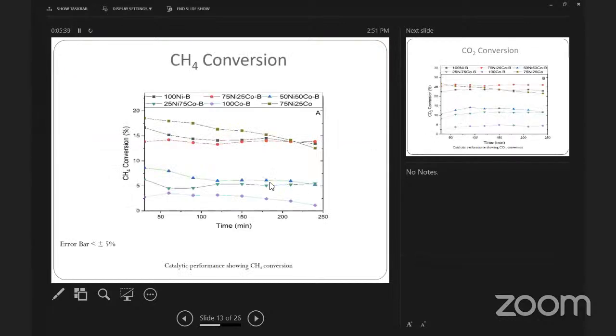Here's the result I got from my reaction studies. We have performed all catalysts, and also compared them with the non-boron catalyst, the catalyst for which we have not used NaBH4. Here we can see that with the NaBH4 treated catalyst, there is a smaller decline compared to the catalyst without NaBH4 treatment, and also the bimetallic catalyst